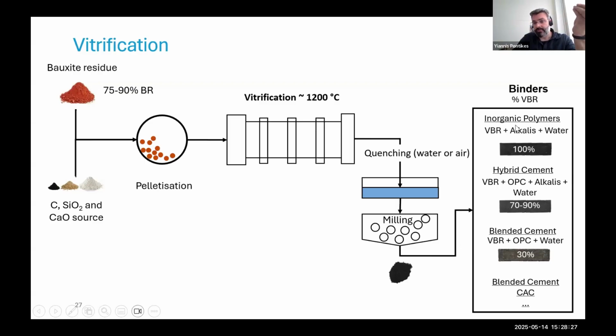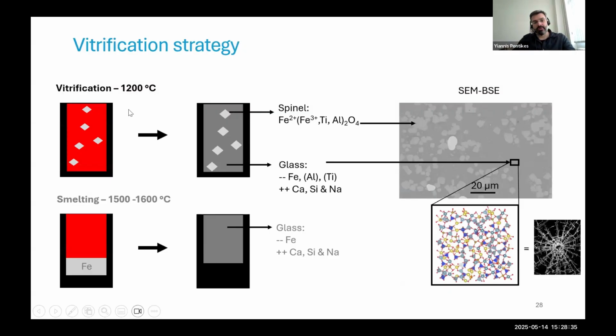Now you can do different things with the powder. You can make inorganic polymers. I will explain that. Hybrid cements, blended cements with Portland or with calcium aluminate cement. During the vitrification, you see here what's going to be happening. You also make spinels. Love the spinels, please, because they take some of the nasty elements. Also chromium will go there and it will not leach afterwards. Or you can also have iron. Of course, you can do smelting. You can reduce all the way down to iron. Then you have a glass that is now depleted in the iron, of course, and it has more calcium, silica, and sodium. This glass is more reactive than this glass, but of course that implies higher temperatures and of course more reductants to get it done.